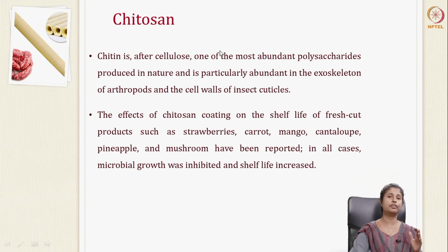Chitosan, we saw the same thing when we talked about biodegradable plastics. Chitin, after cellulose, is one of the most abundant polysaccharides used for edible coatings, especially abundant in the exoskeletons or shells of arthropods and the cell walls of insect cuticles. So what is the effect of chitosan coating on the shelf life of fresh cut fruits and vegetables? They have found a very good, positive effect on the shelf life of strawberries, carrots, mangoes, cantaloupe and mushrooms. Because chitosan has antimicrobial properties, in all these cases microbial growth has been inhibited and shelf life has increased.